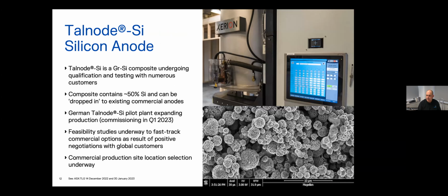Silicon we've mentioned lately because it's growing quite quickly. So you need silicon, you don't need silicon, there's an interest in silicon. We have been developing silicon anode products for several years now. We're in our Gen 2 version. It contains about 50% silicon. The rest is graphite and graphene, which helps cope with the swelling of silicon. When it gets charged and discharged, it tends to swell and crack, and so it's not easily usable in batteries.